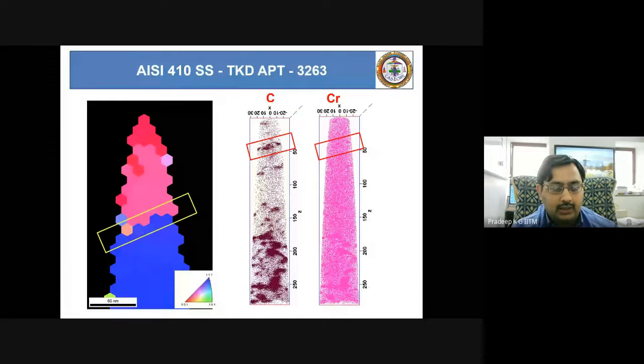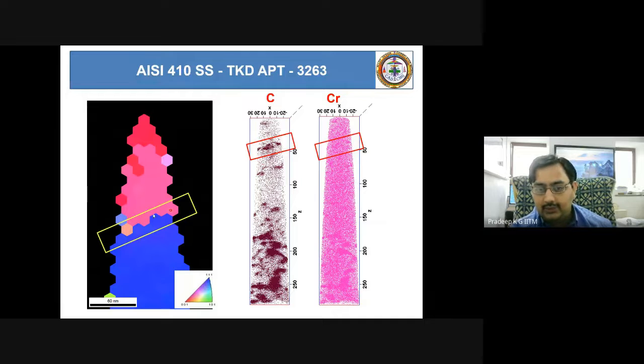Similarly, we can do it on any kind of a steel. So this is an atom probe needle on a grain boundary. The two color difference indicates that there is a grain boundary separating the two different orientation of the grain. You put this in an atom probe and you can see a carbon segregation on the steel sitting on a grain boundary, whereas there is no segregation much across the grain boundary. So all of these correlative things you can do these days to identify the nanoscale chemical distribution and the nanoscale phases present in a composite material.